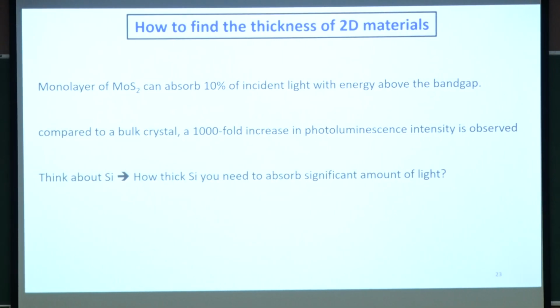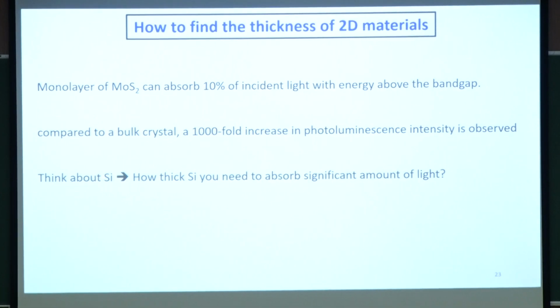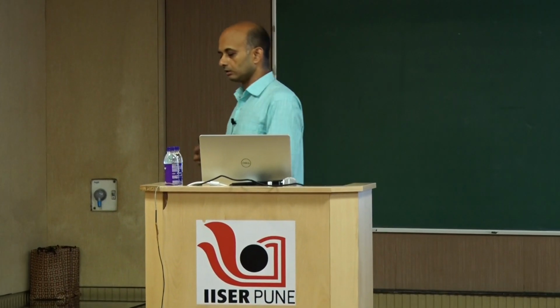Just as an example, monolayer MoS2 absorbs almost 10% of the incident light, where the energy should be above the band gap. If you compare with the bulk crystal, it is almost a 1000-fold increase, and that is the reason you see this high photoluminescence in this material. And just compare with silicon, how much light you absorb. The reason you cannot make an ultrathin silicon solar cell is that silicon has an indirect band gap, so it is not very efficient. Normal silicon, on average, absorbs only 35% or so, even thick silicon, whereas a monolayer MoS2, which is 0.7 nanometer thick, can absorb 10% of the incident light, which is amazing.